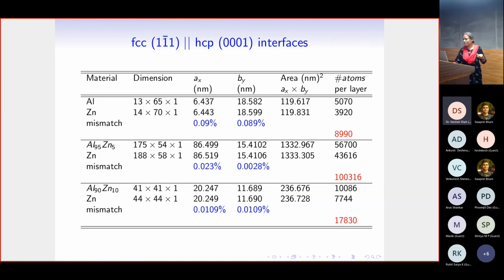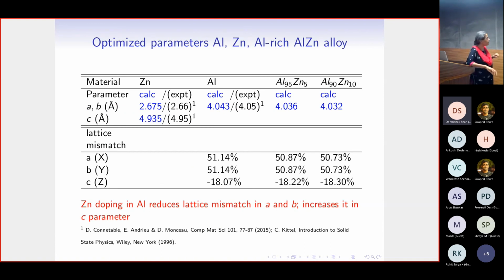Because when we look at the lattice mismatches, this is what we calculated. Pure aluminum with pure zinc, I have a 51% lattice mismatch in the A and B direction. If I put in zinc in it, based on the dopant concentration, this mismatch reduces. And when we say reduces, it really doesn't reduce very much. From 51%, it has come down to 50.8 or 50.7. In 5%, it comes down to 50.8, or you could say 50.9, and in the other case, it comes down to 50.7. Because there is a very small amount of zinc, the lattice mismatch is also reducing by a small amount.